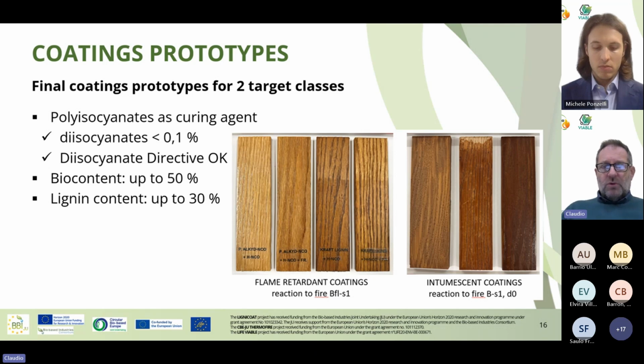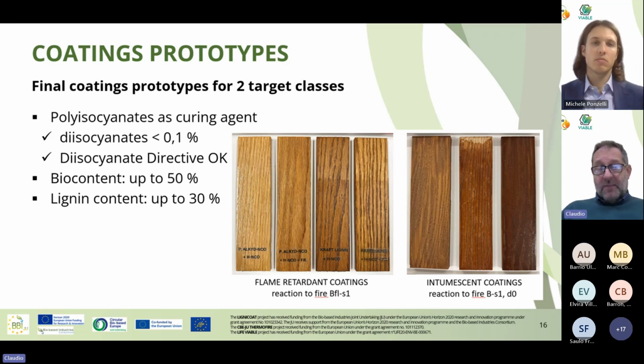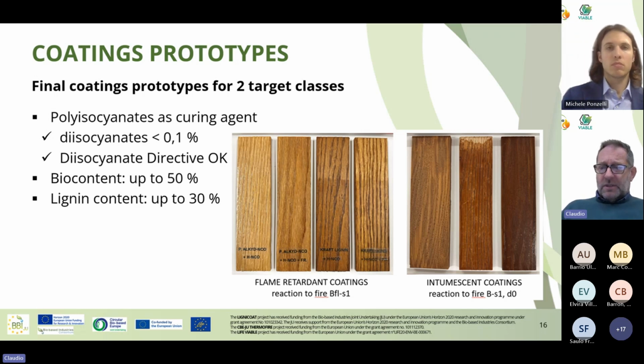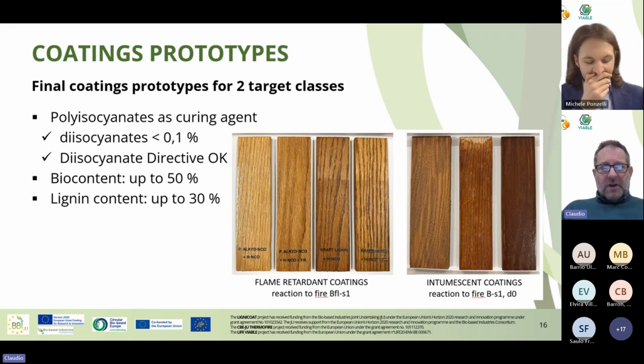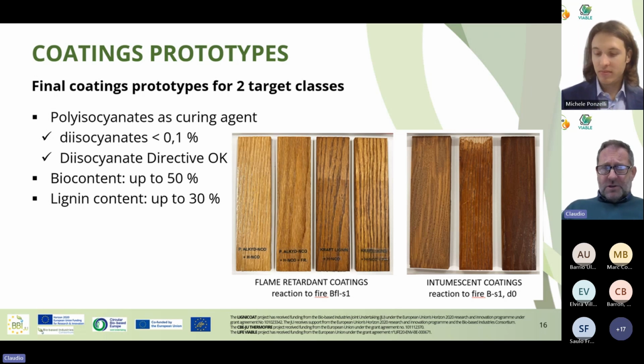We have also found a way to use isocyanates as a directly curing agent to lignin. So to prepare a two-pack coating directly using lignin and isocyanates. Some may say now that isocyanates don't make us very happy from a green perspective and an environmental point of view. Sure, they are a dangerous chemical. They are the subject of the diisocyanate directive that puts limitations on them and considers them as dangerous, to be treated as dangerous in the workplace and so on.